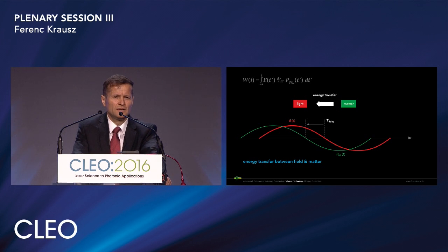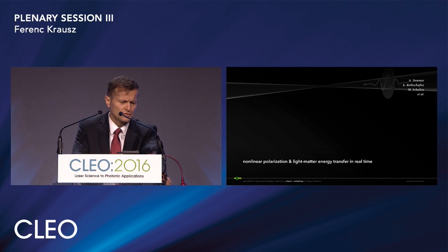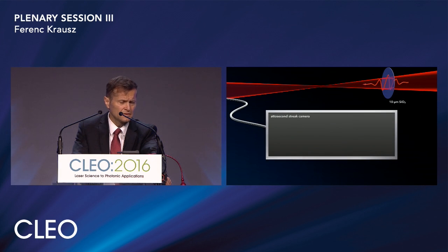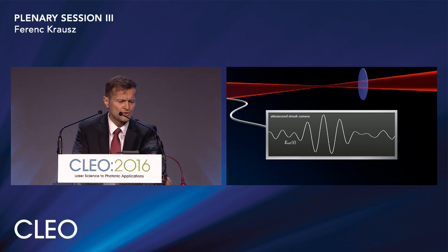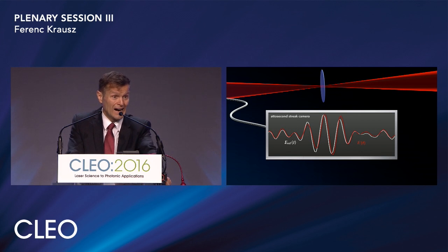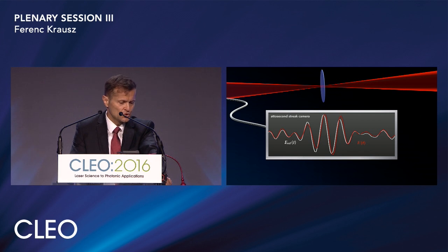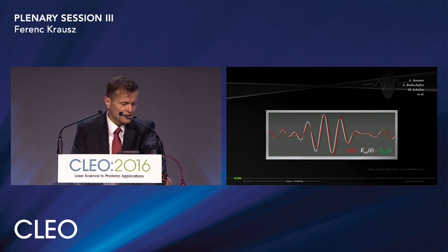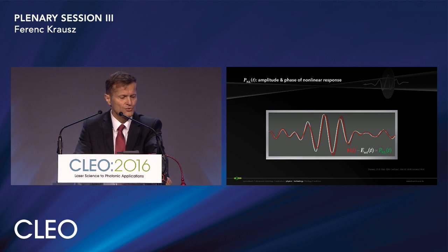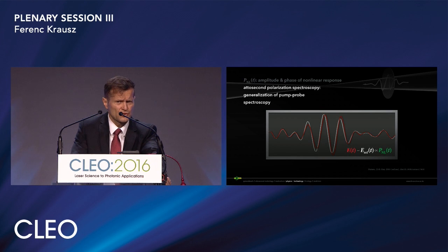Attosecond methodology now allows us to measure this timing. To this end, Ann-Kathrin Sommer and co-workers passed a few cycle pulse through a thin silica sample and measured the transmitted waveform at low and here in the focus at high intensity, at strong field strength. Both measurements have been performed by attosecond streaking. The difference between the two normalized waveforms is directly proportional to the nonlinear polarization induced by the strong field, providing direct access to both the amplitude and the phase of the nonlinear response of the electronic system. We have dubbed this technique attosecond polarization spectroscopy.